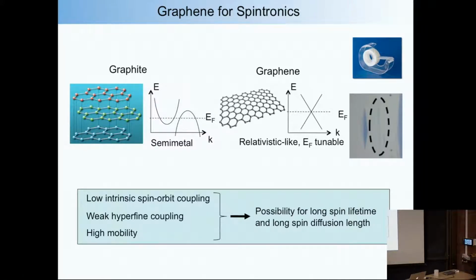And so in graphite, it's a semi-metal. Here's the upper band and the lower band, and they cross. But when you have a single layer, you get a very different band structure. It's a linear band structure. It's relativistic-like. And because it's very thin, you could apply electrostatic gates, and you could tune the Fermi levels, so you could have electrons or holes. And nowadays, this material can be made by chemical vapor deposition very well. But it's still very useful to just use the old method of Scotch tape, and you could exfoliate small pieces